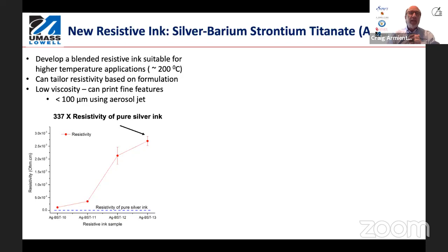Another area that we needed was a resistive ink. A lot of the carbon inks we worked with were not easy to control in terms of their consistency and their ability to print with very fine lines. We developed an ink. We basically said, let's take a silver ink and make it worse. Let's make it resistive. And we chose to use this barium strontium titanate as a particle to actually reduce the conductivity and create a resistive ink that we can control.